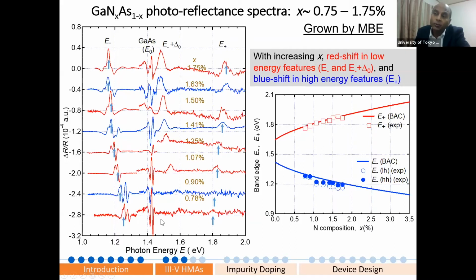One band is lower than the gallium arsenide band gap, another band gap is higher than the band gap. And with this picture, I draw again here that with increasing nitrogen concentration, we have extra two band gaps. And by the amount of the nitrogen, we can play with the band gaps, okay? So with that, if we have 1% of nitrogen, in the previous slide, I wanted to show you that by adding 1% of nitrogen, we can reach the theoretical limit of 63%.